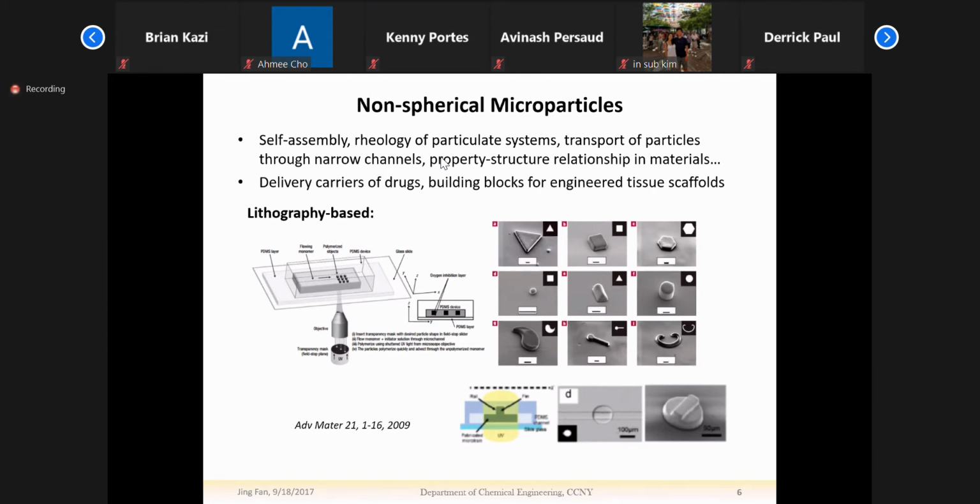You dissolve the so-called monomers, the molecules before polymerization. They can dissolve in water, for example, at a certain concentration, let's say 5% or 10%. Then many of these monomers can be cross-linked by UV irradiation. If you shine UV light onto it, of course, you need to add the cross-linker that I mentioned before, and maybe the photoinitiator.